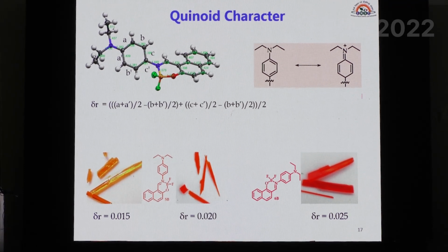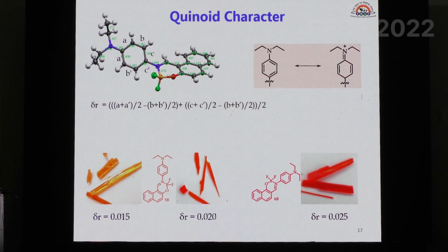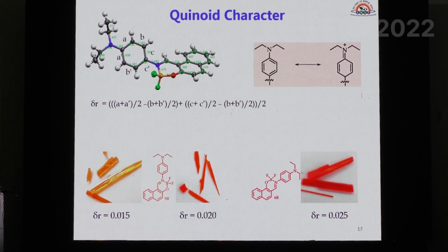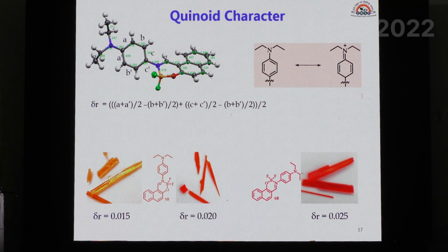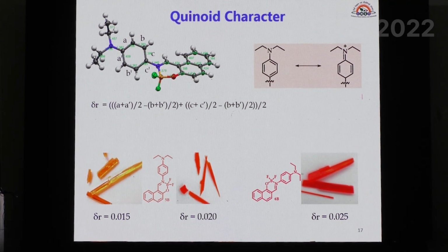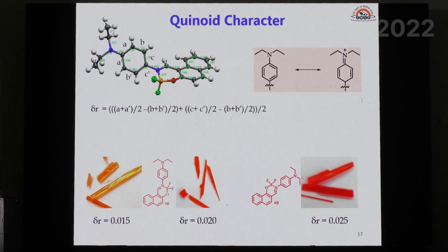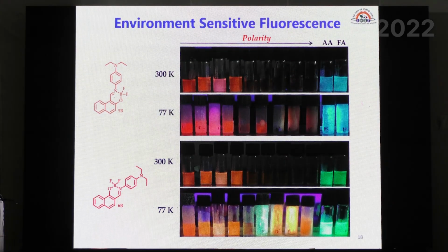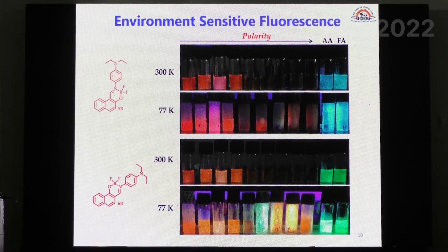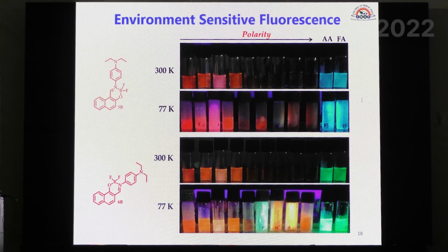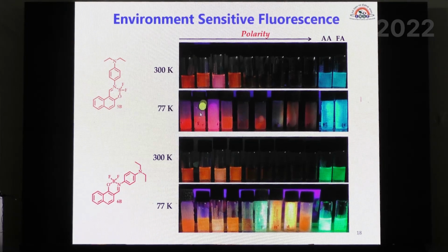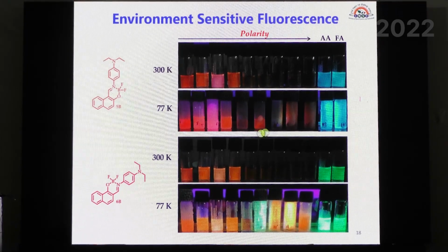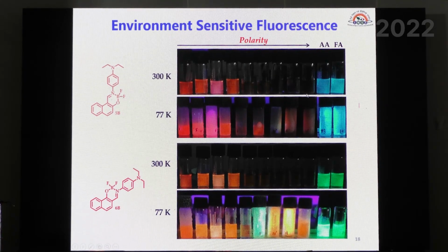So wherever you have strong charge transfer properties, the crystals don't respond to external stimuli. But when the charge transfer is a little less intense, then we see this response towards temperature. And apart from this, in solution state also, these compounds show different colors, again related to this charge transfer property. As you see, depending on the polarity of the solvent, from highly non-polar to highly polar solvent, we see a change in color.